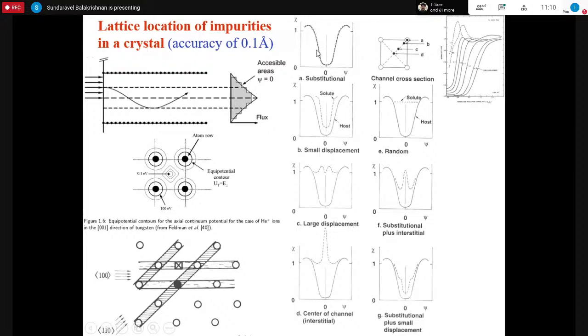So the host lattice as well as the signal from that impurity, they'll be following the same curve. Okay, tilt angular curve. This is substitutional. Suppose you have some impurity atom at the middle of the channel, then that impurity atom will be seeing the high dense flux. Because of that, if it is interstitial, then at the bottom left of this curve, you'll be seeing some sharp bump. And if this curve is like this, then we can tell that impurity is in interstitial position.